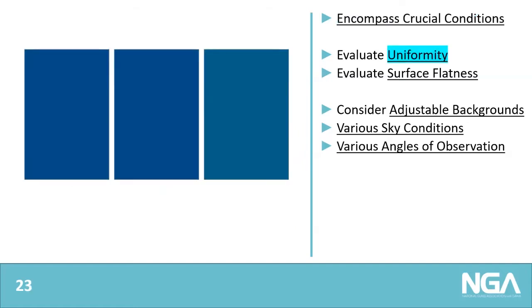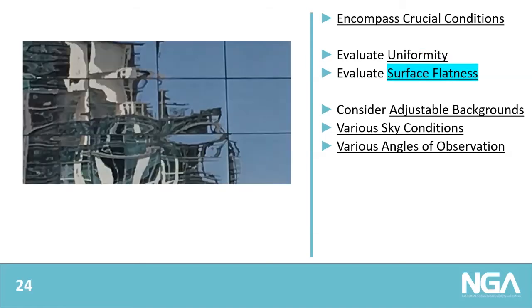We want to evaluate uniformity, of course, and as you can see on the screen, the panel to the right has a slightly different color than the other two. We want to consider surface flatness. Of course, there's a lot of distortion here, and if we see something like this in terms of the mock-up, we would want to evaluate the flatness of the glass. And a little bit later in the presentation, we'll talk about how we can introduce a specification to address the glass flatness physically. We could also consider revisiting the glazing construction and deciding upon a composition with less outward reflectivity, so there's less visual prominence to the distortion.